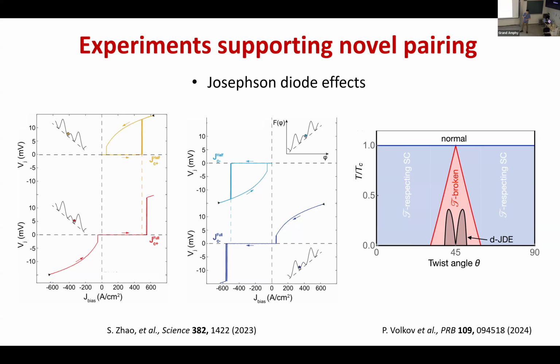There's no heating, at least for this reading. You go to the zero resistance state, and then there's no heating, so then you have a jump. Their argument here is that usually you have the washboard potential for the Josephson effect, but due to this higher order coupling, each of the quantum wells has a double minimum. So then you can have different preparations, because you have the phase particle in either one of the minima or the other. That gives you different critical current.